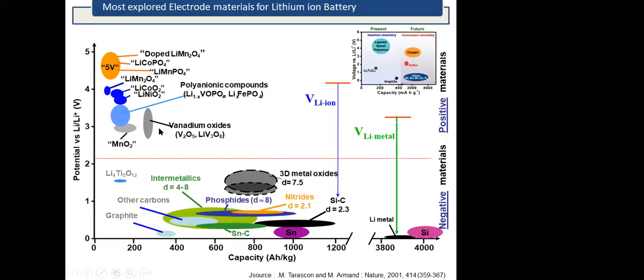Based on the voltage, here are mostly commercially available batteries, or you can say the most prominent cathode and anode materials. Here you can see most of the cathode materials have more than 2 volts, reaching up to 5 volts. And the anode, you can see, is less, nearly 1.5 volts. If you take graphite, it has nearly 0.1 volt. Then other forms of carbon, hard carbon, soft carbon, and mesoporous carbon are used as anode material.